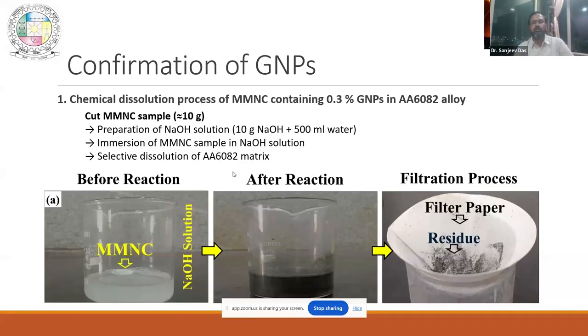So initially, to understand that, we went with a very smart idea: let us dissolve the aluminium in sodium hydroxide solution. Aluminium will react and dissolve, but the carbon will not. So we took water, added 10 grams of sodium hydroxide to it, got the solution, and added our composite material. So what happened? Aluminium went into the solution, and the liquid turned black, and then we filtered it.